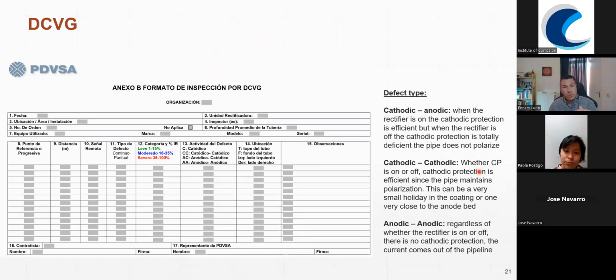And also, if we switch off the CP system for a few hours or days, the coating keeps the polarization in the pipeline, and that specific defect is going to be protected for a couple of hours or days. And the worst case scenario is when we have a defect that is anodic. So even if the CP is on or off, it's going to be corroding. Usually, despite the size of the defect, all those classified as anodic should be repaired, even if they are small. And this is one example of how you can record your findings.